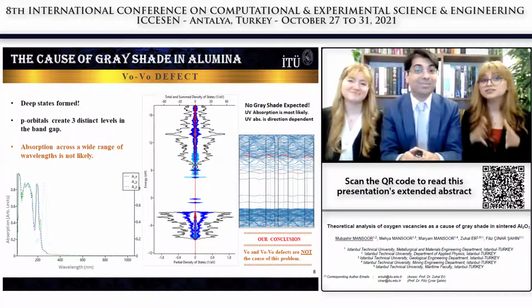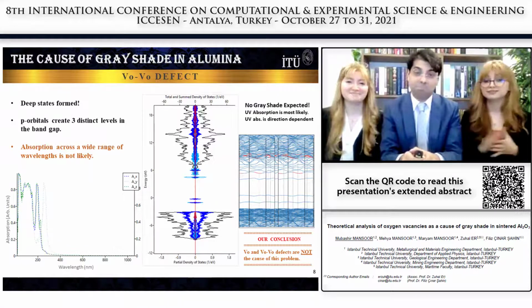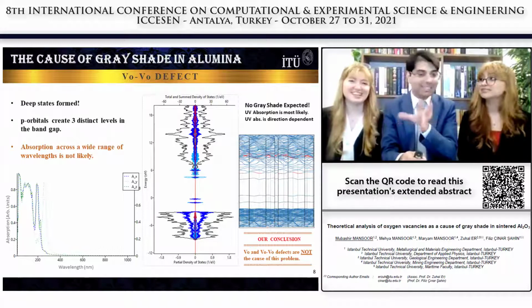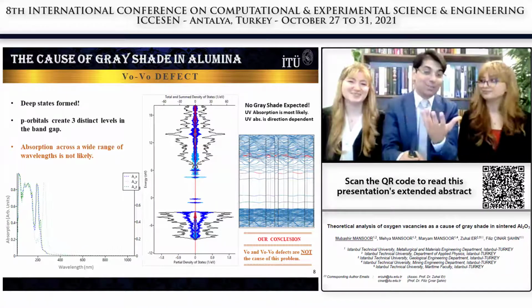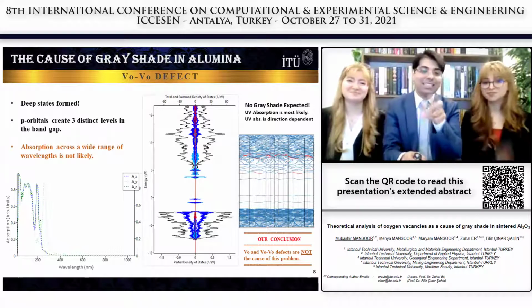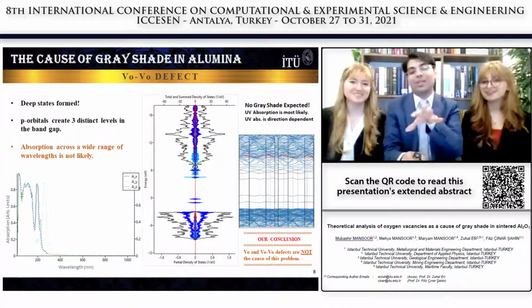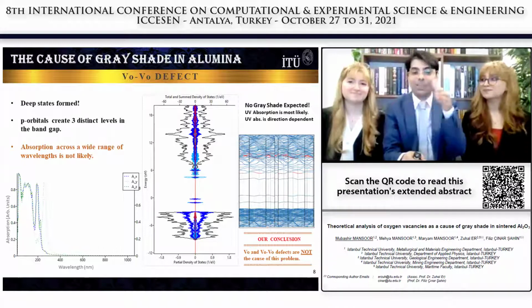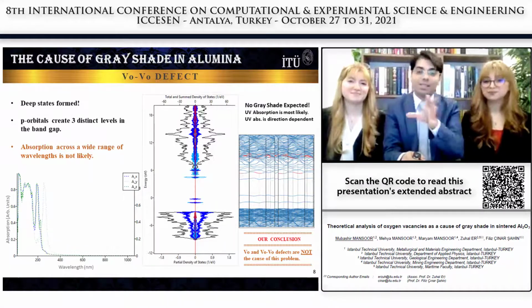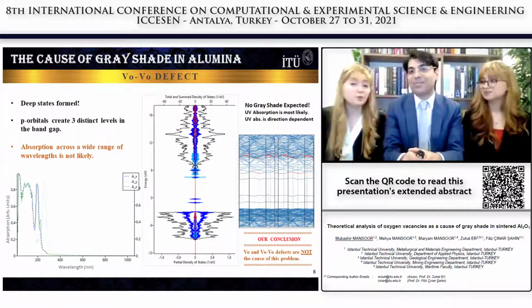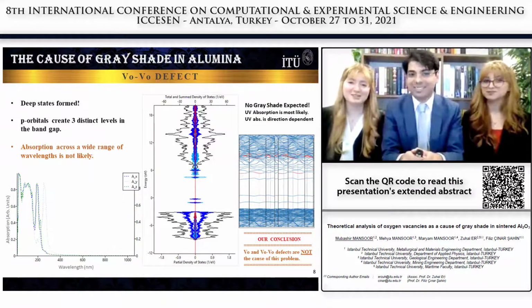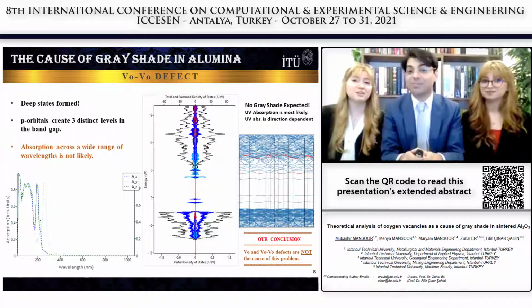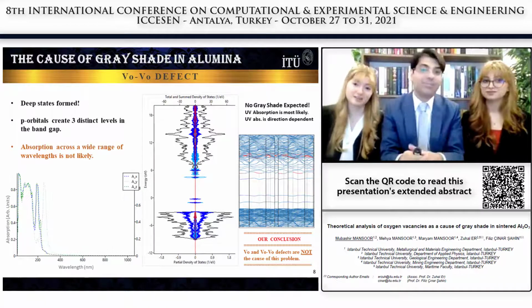There is also a difference in the UV absorption with respect to crystallographic axis. Now, this is kind of expected since sapphire or alumina is anisotropic. Yeah. So it's interesting to see that there are two different peaks occurring with respect to orientation, so in the X or Y or the Z direction. But again, there is no continuum in this case either. So we cannot expect a grayish color from the di-vacancy defect as well.